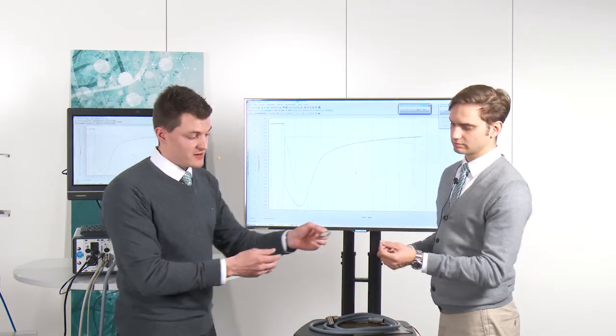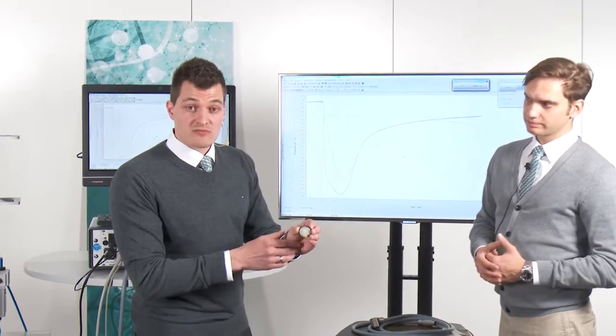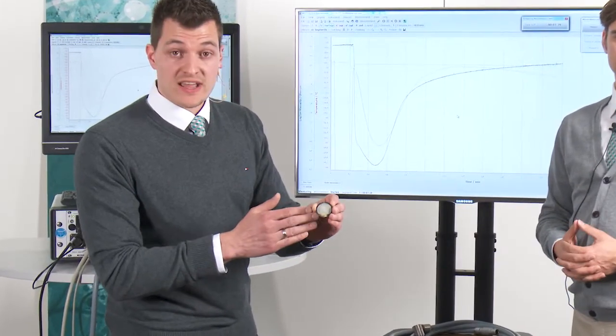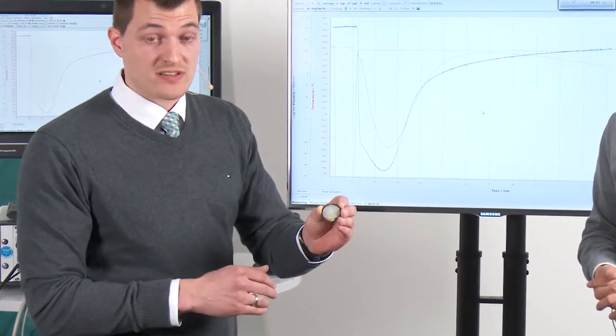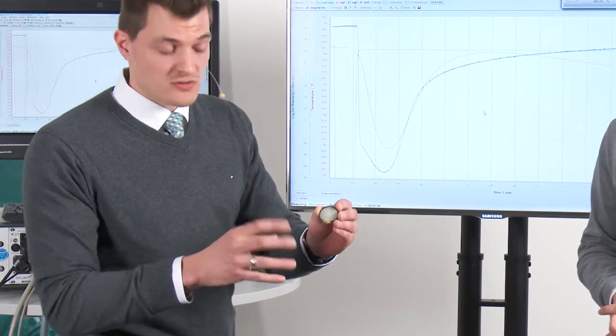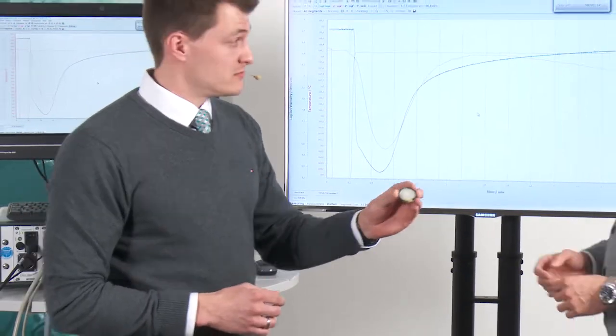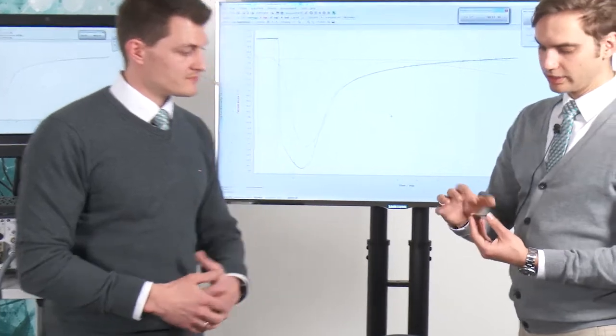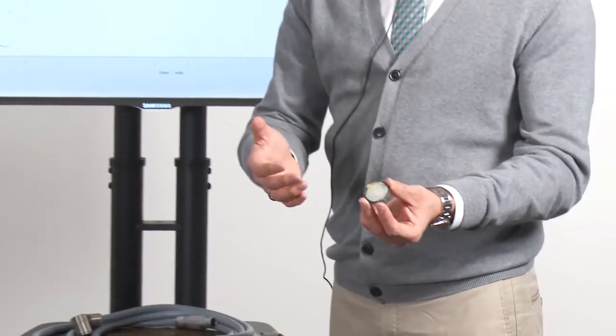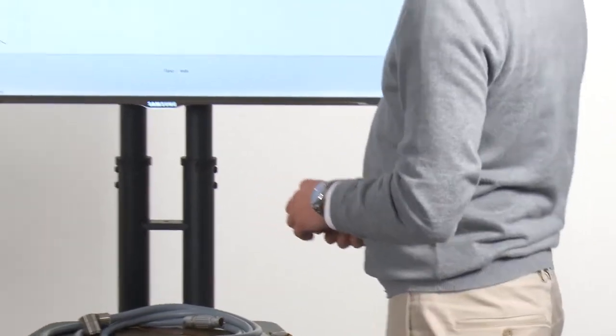Yeah, you can see that also here. You can see a glass fiber woven fabric between the dielectric electrodes and the carbon fiber material here. So the resin can feed through and the carbon fiber doesn't. Camera can zoom in a little bit. Yeah, you see this is quite convenient. You just put it onto the sample and that's how it goes along.